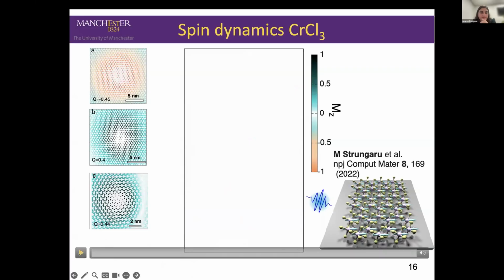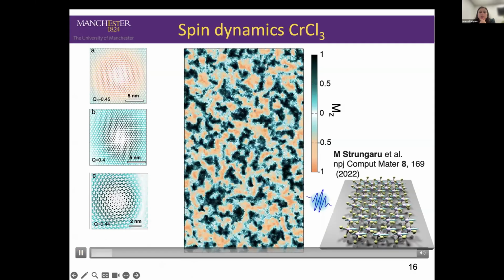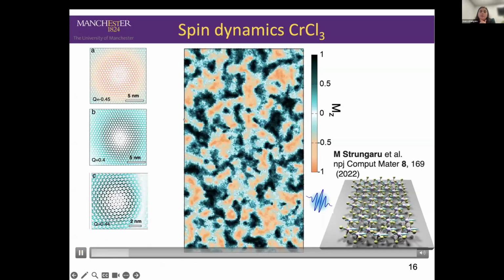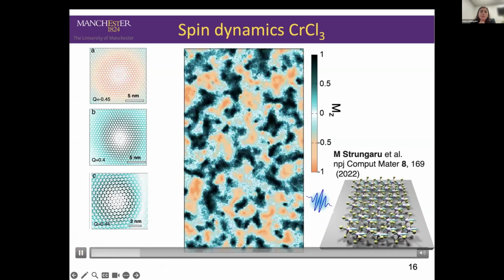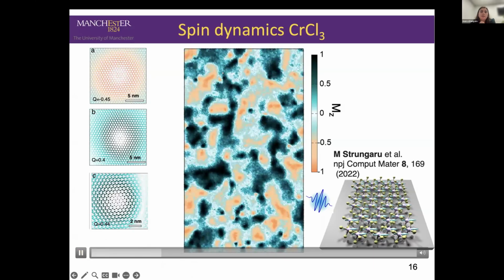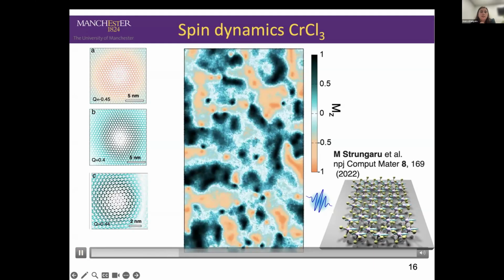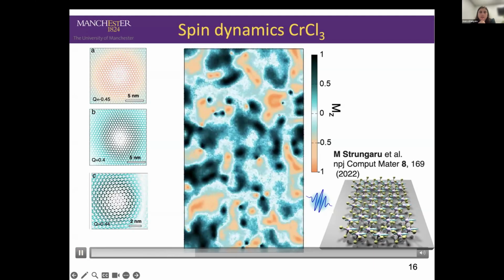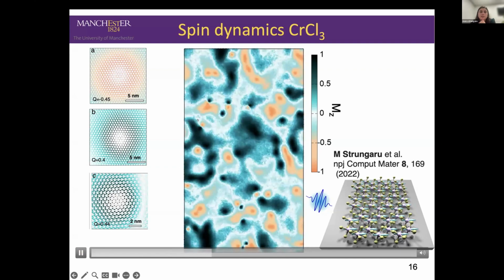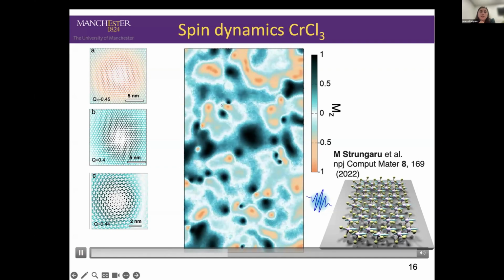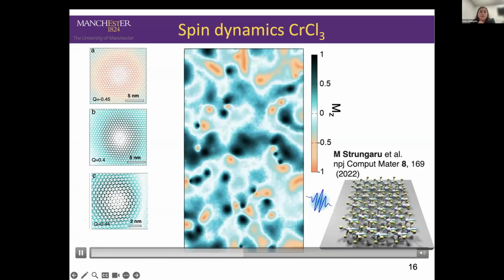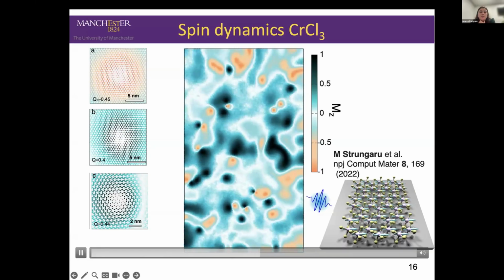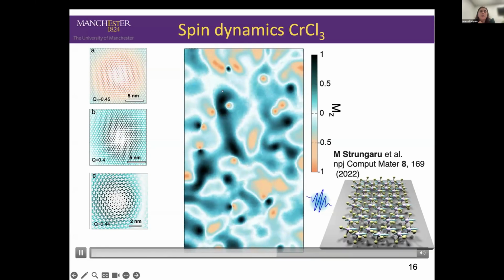There's an animation here. So for this, we can shine a laser pulse on our 2D magnetic system. We observe at the beginning a lot of thermal fluctuation, a lot of thermal noise. And then what we observe is that our system relaxes and these areas are created, like the dark green and the orange areas.